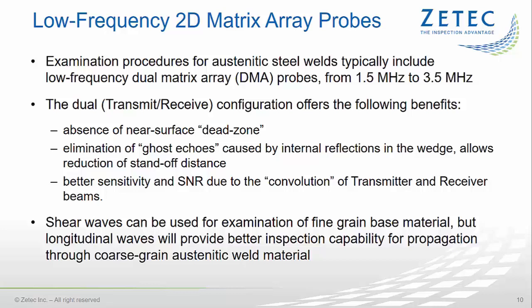But most of all, the convolution or overlapping of the transmitter and receiver beams results in a better sensitivity and signal-to-noise ratio. And let us constantly keep in mind that shear waves can be used for examination of fine-grained base material, but L-waves will provide better inspection capability for propagation through the coarse-grain austenitic weld material.